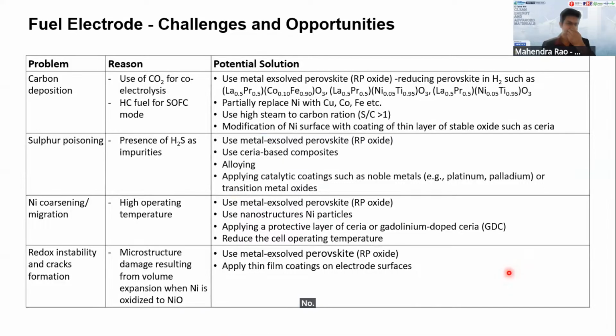I just highlight some of the typical problems. There are many problems. These are very common problems that normally we face for the fuel electrode. The main problem we normally face is carbon deposition. This is due to the carbon-based material that we use at the electrode. For example, for co-electrolysis, we use CO2, water, and hydrocarbon fuel for SOFC. Of course, we will face the carbon deposition.